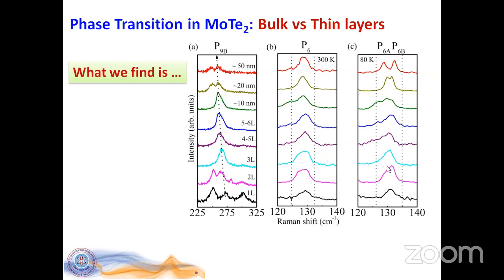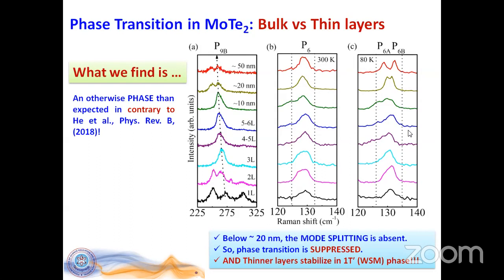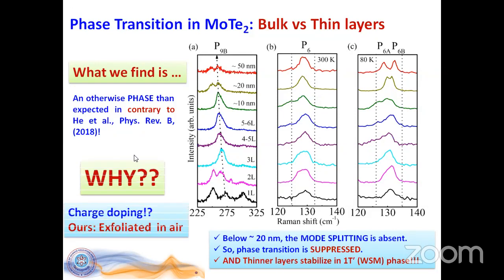Sure, sure. And then for the other thicknesses, I can see the phase transition is lost. So that basically establishes that we also see that the phase transition is lost. But contrary to what they said, the phase that they showed was the Td phase, which is the orthorhombic phase, but in our case, it is the high temperature phase, which is the monoclinic phase, right? So that is the contrasting observation that we have compared to the previous data that we showed.